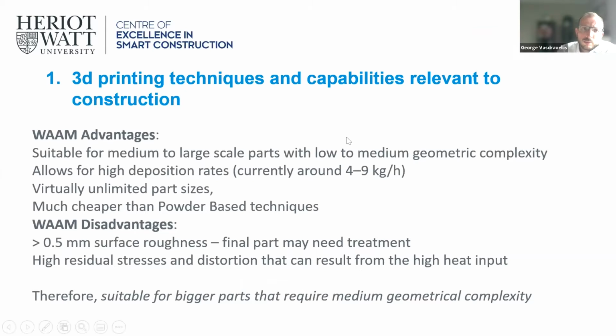So the advantage of WAAM is that it is a technique that's suitable for medium to large-scale parts with low to medium geometric complexity. With this technique, we cannot have very, very complex parts, but it's okay to have low to medium geometric complexity. It allows for higher deposition rates as compared to PBF. So currently it's 4-9 kilograms per hour, as opposed to 50 grams per hour for the PBF.